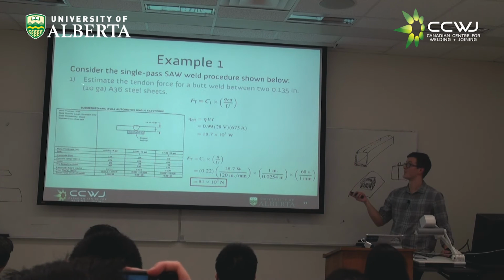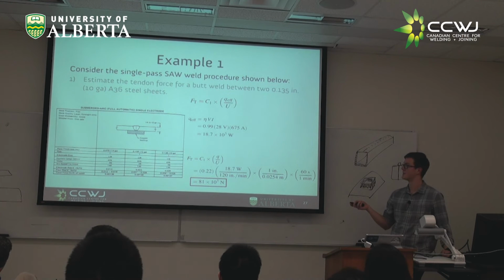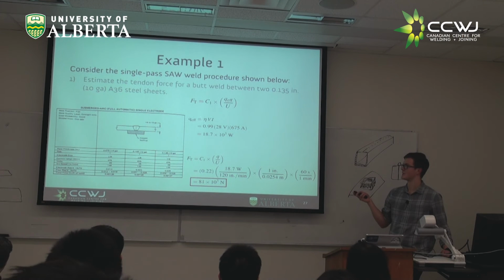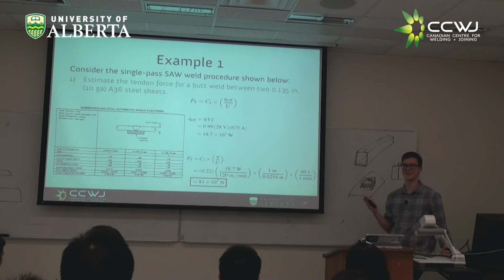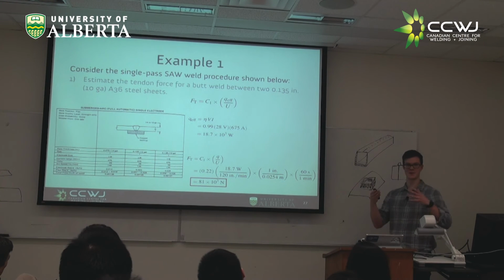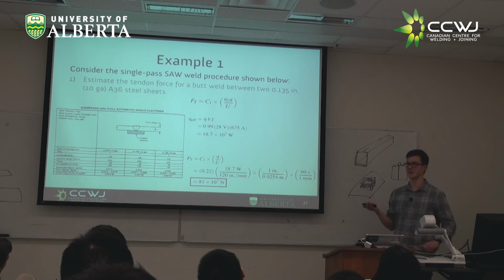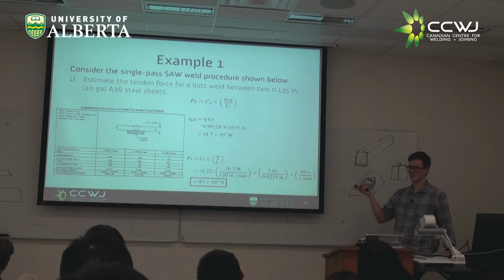We have our procedure for welding this with submerged arc. We see this last thickness corresponds to it. First step is going to be to calculate our effective heat input. Now our effective heat input is eta times voltage times current. So if we look for eta, it's not here, but does anyone know? Well, it's up here. Eta for submerged arc welding, give around 99%. When you have the flux on top of your weld, it helps kind of trap that heat. So you can argue, and you'll see different publications, but as a reasonable value, about 99% of the heat in submerged arc welding gets into the weld. Is that accurate with what was in the formula sheet?